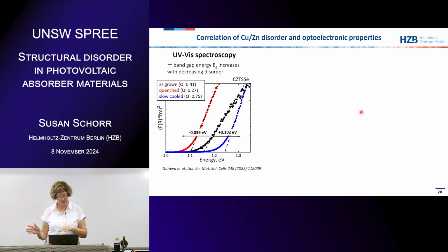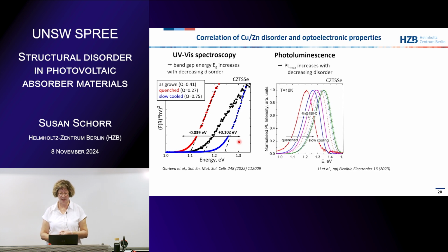And now we know what happens, and so we could interpret UV-Vis data from, for instance, here for copper zinc tin sulfide selenide, 3 different samples. The black curve is for as-grown powder. Then the red curve is for quenched, that means very fast cooled powder. And the blue one is for slow cooled powder. And you see that the order parameter changes, so we have the highest disorder, of course, in the quenched sample and the lowest degree of disorder in the slow cooled sample. And with this, also the band gap changes. So it's the same material chemically, it's only the degree of copper zinc disorder that changes, and with this changes the band gap.